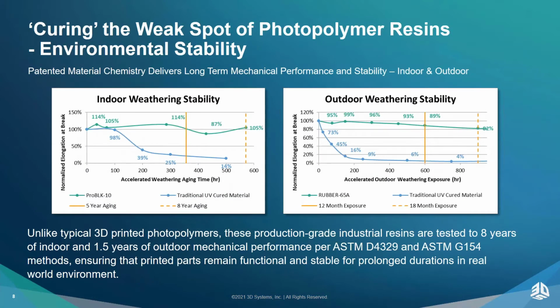So like I said, after we developed these acceleration factors, we then developed some very novel chemistries and chemistry packages that were providing us best in class and really unparalleled weathering stability that you don't see in the additive space. As Marty alluded to earlier, additive parts and UV photopolymers specifically are very well known for becoming brittle over time. This is only exacerbated when you put them outside with a combination of both sunlight and moisture. This combination really drives the degradation of the polymers.